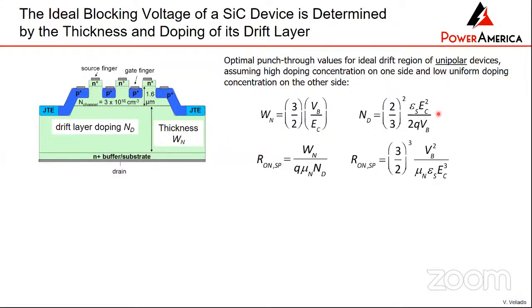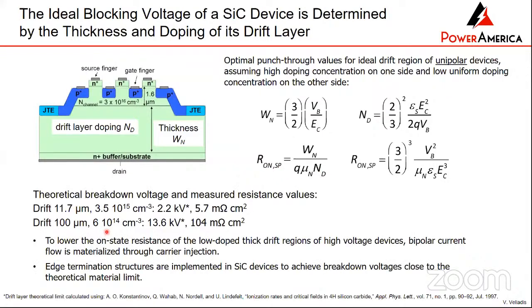And also, this equation tells you, for a specific voltage that you're interested in and the critical electric field of silicon carbide or whatever power material you're using, the optimal doping density. So you have the thickness, the doping density, and the resistance of the layer through these equations. And just to give you an example, if you want to make a device that will do 2,000 volts, this layer needs to be about 12 microns thick. If you want to make a device now that's able to withstand 10,000 volts, then the thickness of this layer needs to be 90 or 100 microns, roughly speaking.